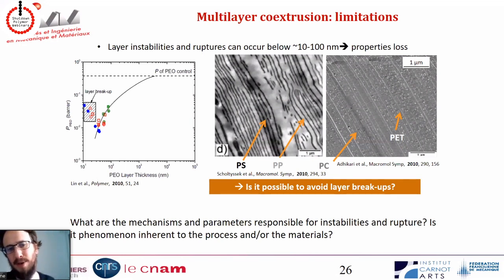And now the last part of my talk is about limitations of the process. So right now I showed nice applications. I also showed that you can raise some fundamental questions with this system. And now I'm going to talk about things that don't work that well. If you remember this plot I presented before, this is the permeability of the PEO, and it decreases with decreasing thickness. And by looking at the shape, you can say, hey, maybe if I go from 13 nanometers to 10 nanometers in thickness, I can gain 1 more order of magnitude. So let's try that. Of course, Baer's group tried it, but actually the permeability goes up again.